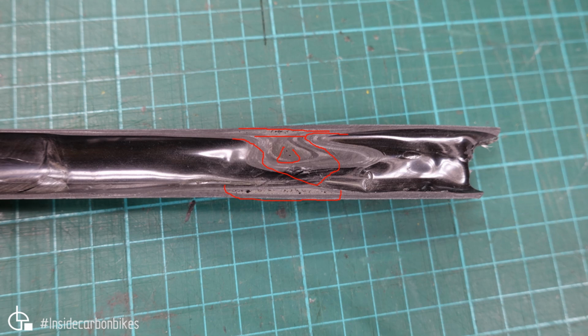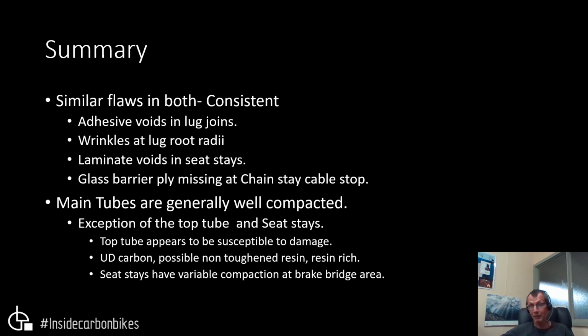So that's typically what causes these crack indications. These, what people call paint cracks. There's no such thing as just a paint crack. It's usually there's either a ply step or a wrinkle underneath. That's what's usually going on. So that's two of the same model of frame cut up, and from what we saw, the flaws were pretty much the same type of flaw, same location on both frames. So they were consistent. So now they just need to be consistently good in those areas, as opposed to have flaws in those areas.